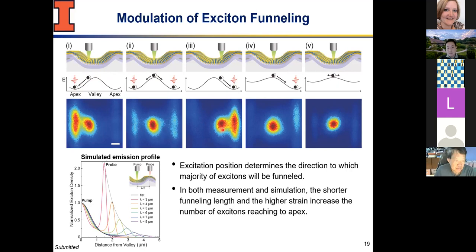A little offset pumping, or in this case, if you have a sample that has an unequal energy gradient at the left and right, you can see that at one point you get much more exciton drift than you have on the other. And as I showed you earlier, if there's very little energy difference, they don't go there. So these really taught us and also help us to demonstrate this drift of exciton across the strain gradient.